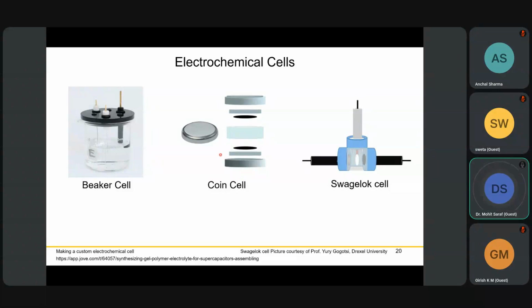But when it comes to supercapacitors, when you have to open and close these cells again, there might be some challenge. In those cases, a Swagelok cell can help, where the amount of electrolyte taken is very low. So we can quickly disassemble the cell if there's any problem and rearrange everything so our system works properly. These kind of cells are highly recommended for supercapacitor testing.